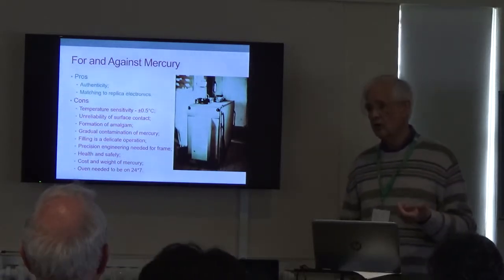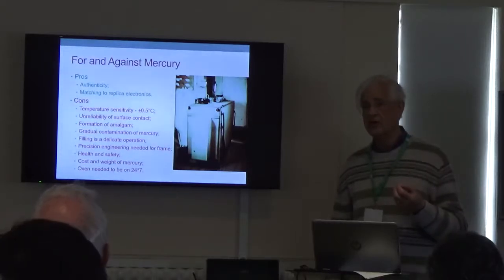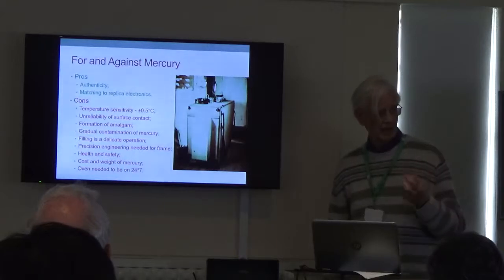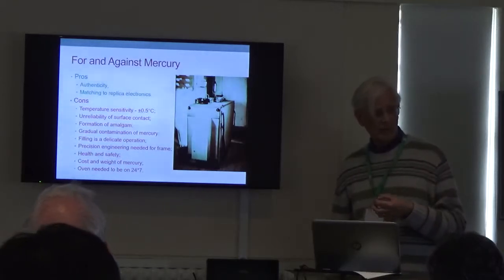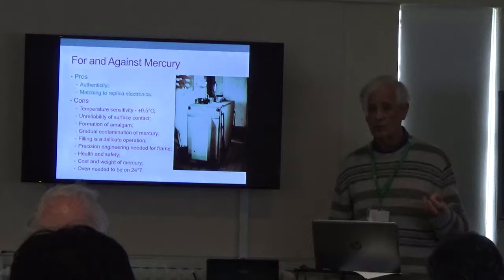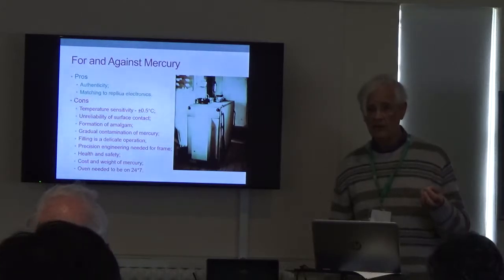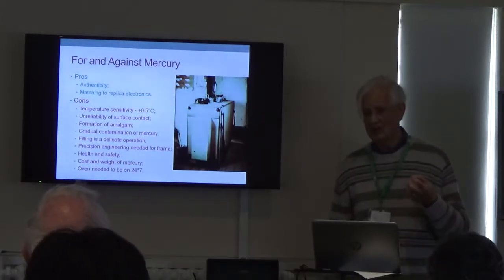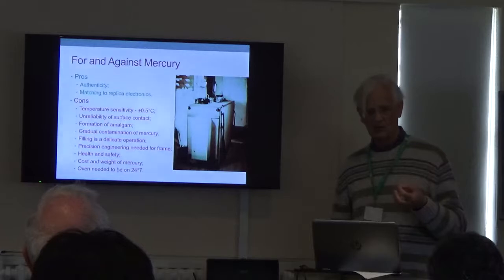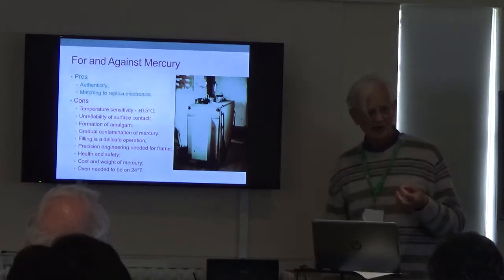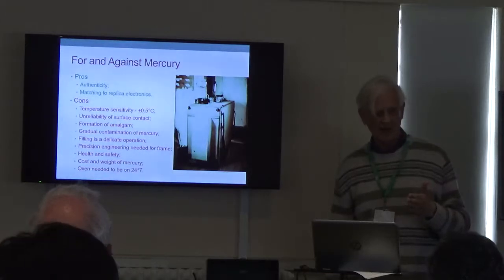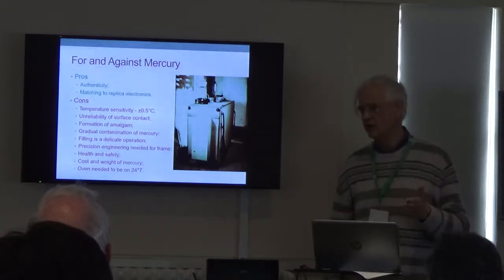The design only works if you get efficient energy transfer between the quartz crystals and the mercury and back again, which implies that the mercury has to wet the quartz, and the quartz crystal has to be impedance matched into the mercury. Mercury doesn't naturally wet quartz, so if you just pour mercury in, you tend to get an air film which reflects the RF back, and you get too much loss of energy.